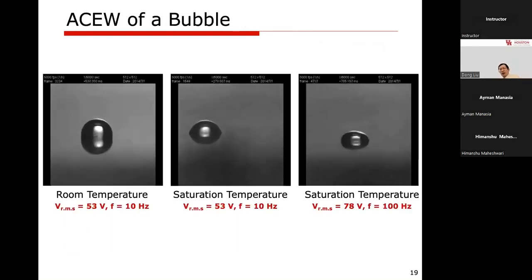So here, even before we do the heat transfer study, we look at the AC effect on bubbles. So those are bubbles, no longer droplets. You see, a root mean square voltage of 53 volts at 10 hertz. This is what you see for a bubble at room temperature. Because this frequency is very, very slow, you can actually see in real time how the bubble responds to the electric field. The contact line is moving. It's like the bubble is shaking. Now we increase the liquid temperature to 100 Celsius at atmospheric pressure, because this is what we actually need for boiling application. Basically similar behavior.